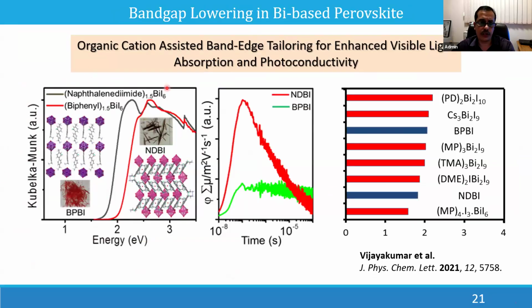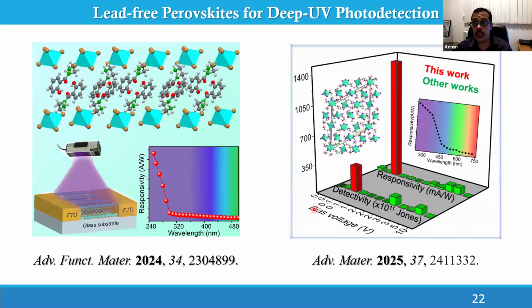Of course, we made several structures and compared them with the literature reports, and we were able to get a band gap which is below 2 electron volt. At that time, getting below 2 electron volt for a bismuth based structure was not reported. In all cases, it was 2 or above, except this case. So we were able to easily achieve below 2 electron volt, and this 2 or 1.5 electron volt is very much suitable for solar cell kind of applications. Of course, this is not good enough for solar cell. We used it for some other applications like photo detector application.